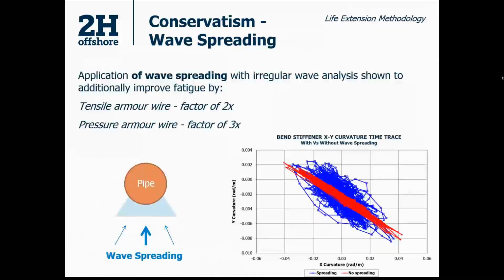Another area of conservatism is the use of wave spreading. So instead of assuming that those regular waves are hitting the pipe in the same direction, same location, they will have different energies as they are impacting the circumference of the pipe. So not only using irregular wave analysis, but using wave spreading, we've seen that applying wave spreading has increased the life of the tensile armors by a factor of 2, and for pressure armor wires up to a factor of 3.